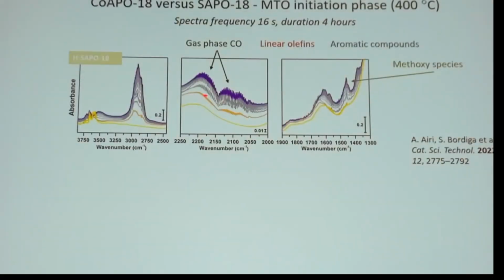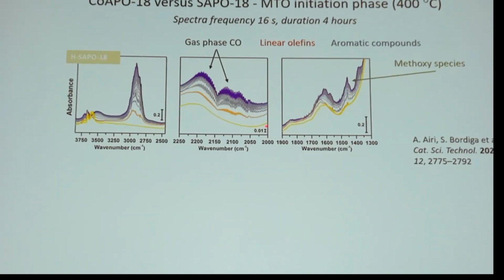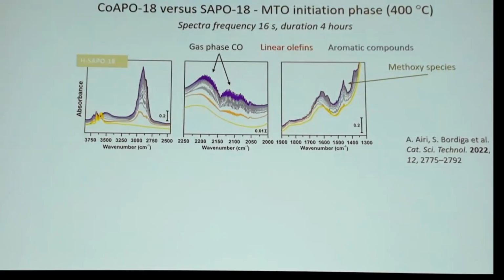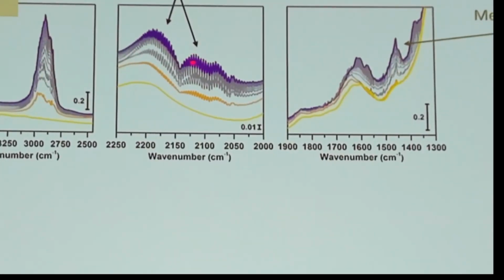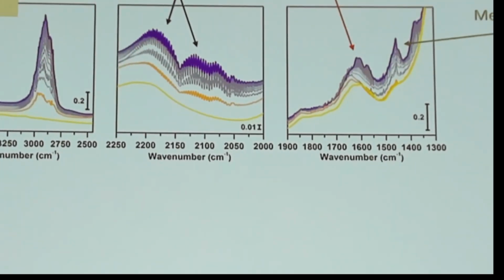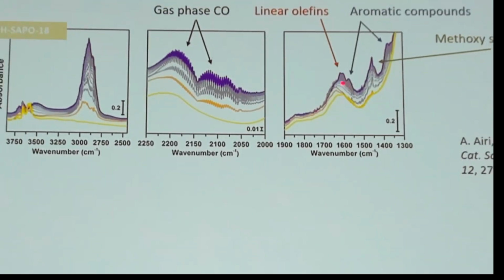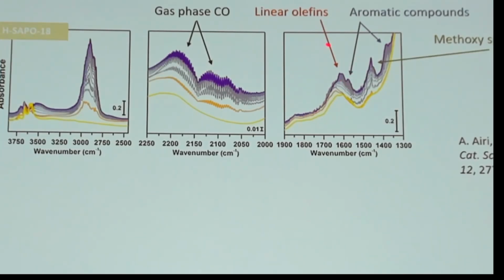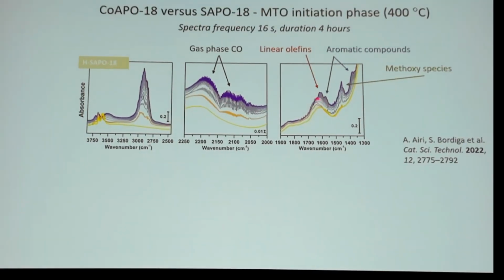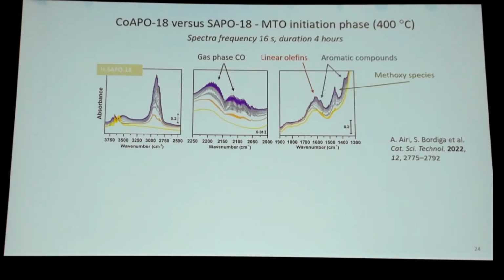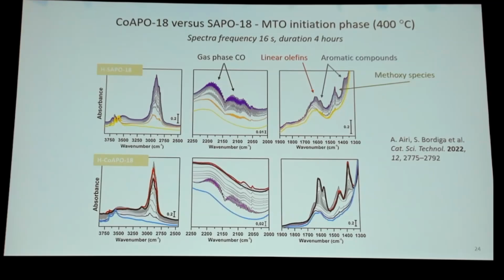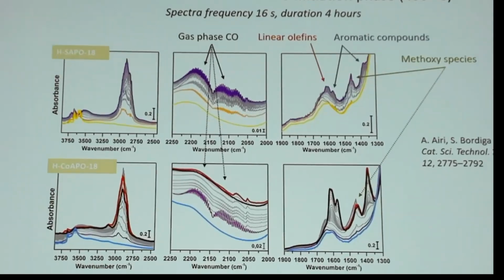And then, adjacent to that, you see that there is CO, gas-phase CO in the cell, that is formed from the methanol, that we can observe. And we see that they are abundant throughout the 4 hours of reaction. We also see that there is formation of linear olefins, as you can see in red here. And there is with time also formation of aromatic compounds, but it is the linear olefins that dominate in the SAPO-18.